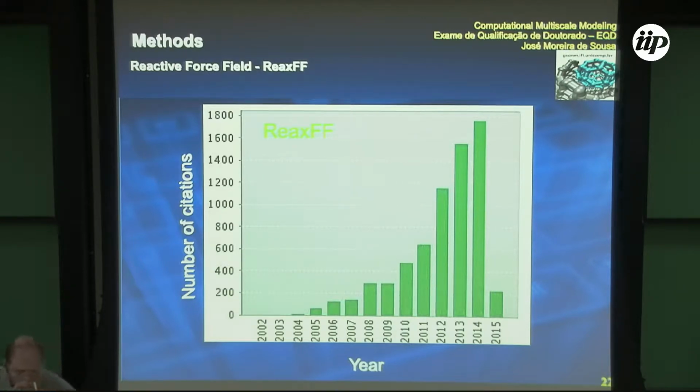So how do you actually make sure that you don't get something else? Like, if you would solve the Schrödinger equation to find the new bonds, you could find something else in terms of hybridization or some other structure that would have smaller energy. The test, in general, uses the heat of formation. It's a check. For carbon-based structures, it's not true for other structures, but for carbon-based structures, the error in the heat of formation is the same as the error in the experiments. We calibrate from DFT calculations if you have them, but most of this data is calibrated from experiments on similar structures. So for carbon-based materials, it's quite reliable.